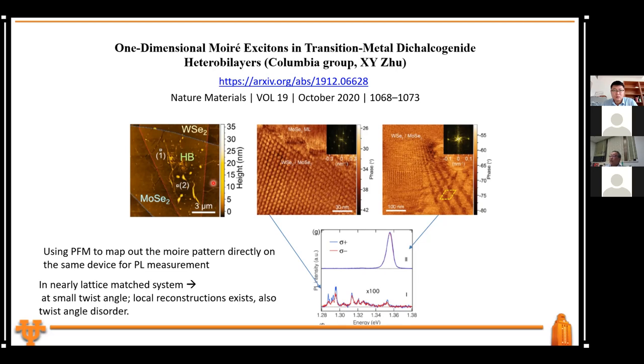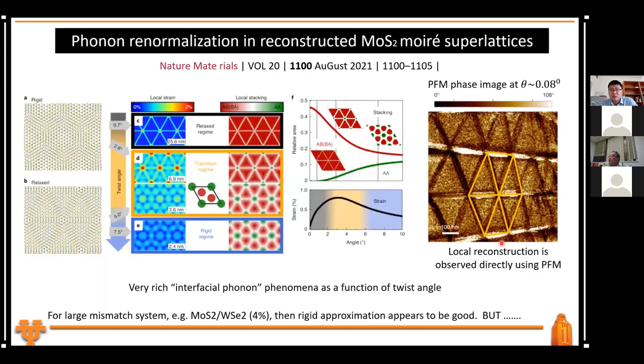And lo and behold, he showed me this PFM measurement with a phase contrast. He can see the moiré pattern, and discovered this moiré pattern varies from location to location, even with your best intention to control the twist angle. There is a lot of twist angle disorder, and that gives rise to totally different results. So that partially explains it, but still, is the moiré potential deep or not? That part is still not answered.